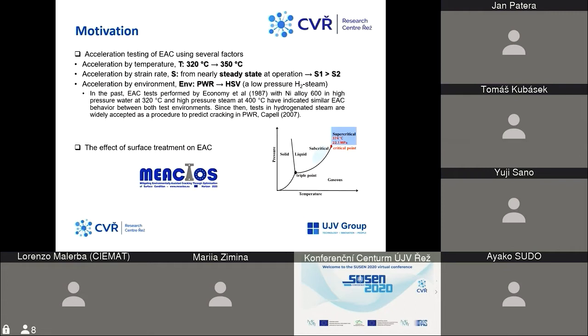PWR environment. It was shown earlier by Economy et al. with the nickel alloy 600 in high pressure water at 320 centigrades and high pressure steam at 400 centigrades. They have indicated similar corrosion behavior between those two environments. So since then, those tests in the hydrogenated steam are widely used as a procedure to predict cracking in PWR.